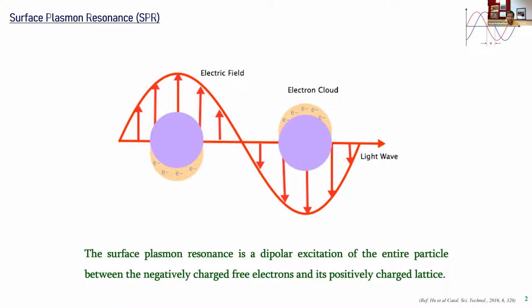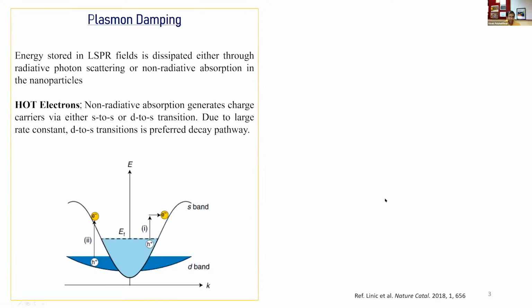When these surface plasmon resonances get damped, you absorb all that energy onto the particle surface. When the plasmon damping happens, that entire solar energy is then used to excite the electron from the Fermi level to some higher level, say through an s-to-s transition or a d-to-s transition. D-to-s transitions are preferred because of the better lifetime. These are called hot electrons because they are now at excited higher levels. These hot electrons can ideally be injected into the CO2 molecule to create a CO2 radical anion, and then you follow the next step of CO2 reduction.